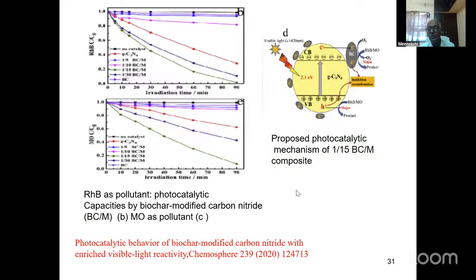By using this 1/15 BC to M graphitic carbon nitride biochar, they have done the degradation of rhodamine B. You can see that this 1/15 ratio is found to be most efficient in the rhodamine B degradation. And this is for methyl orange degradation. So two degradations are given, one is rhodamine B, another one is methyl orange. Again, the mechanism is very simple, the same mechanism I told you for the earlier one: the biochar abstracts the electron and gives it to oxygen, producing the superoxide radical and making an effective separation of the electron and the hole.